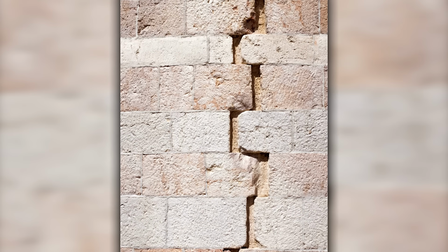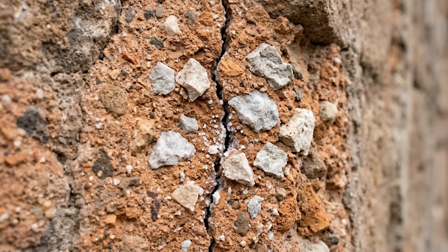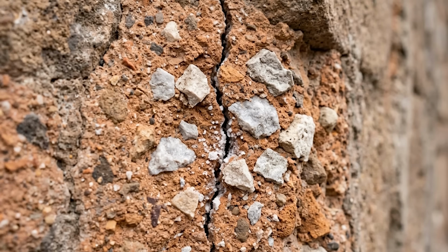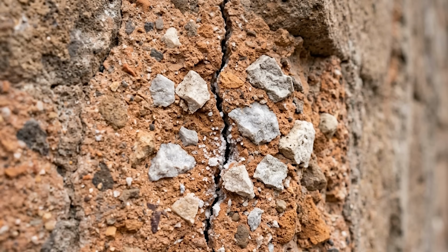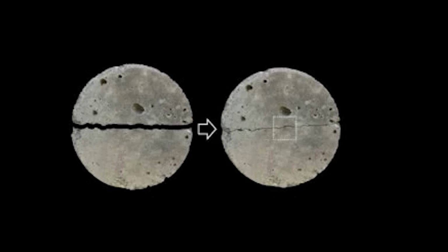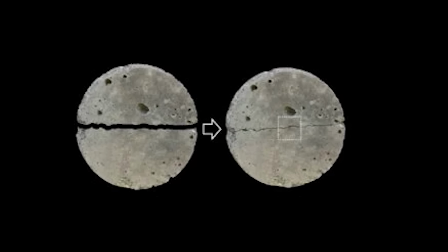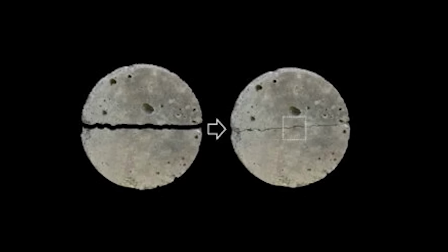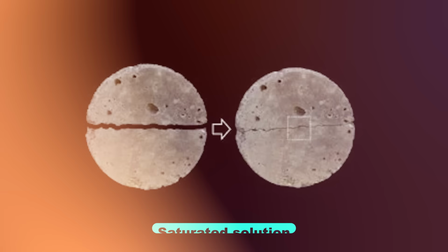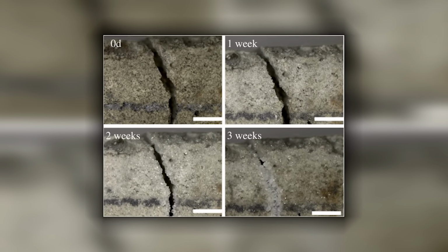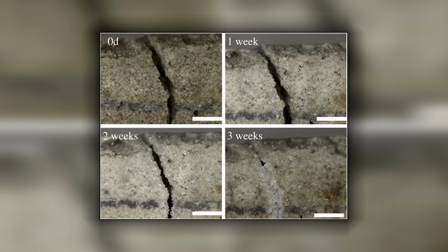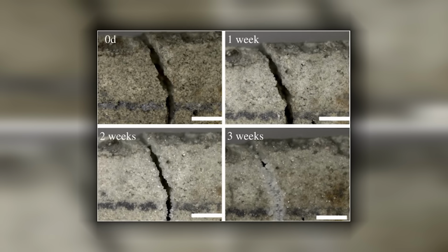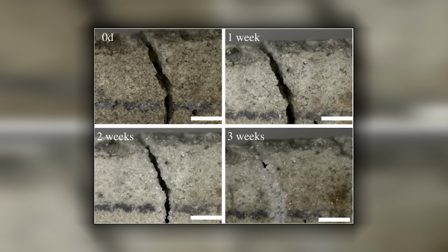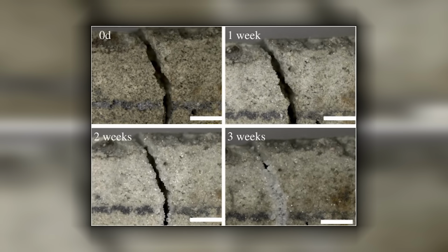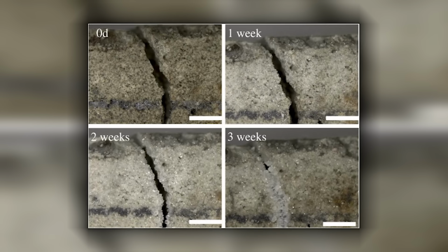Picture a hairline crack opening in a Roman wall. The lime clasts embedded in the mix are reservoirs of unreacted calcium carbonate. When water reaches a clast, it dissolves it. The dissolved calcium flows into the crack as a saturated solution, and when it loses the water by evaporation, it recrystallizes as fresh calcium carbonate, the same mineral. The crack fills itself in real time, and the wall keeps standing.